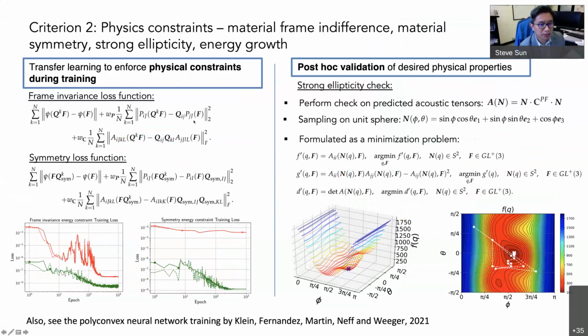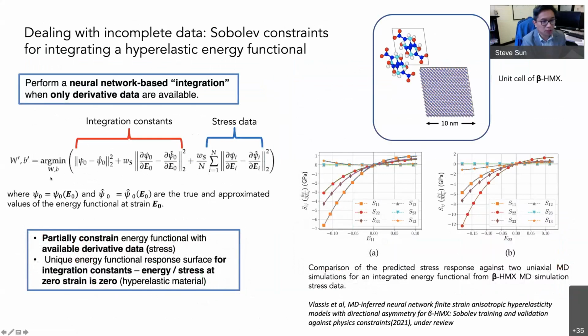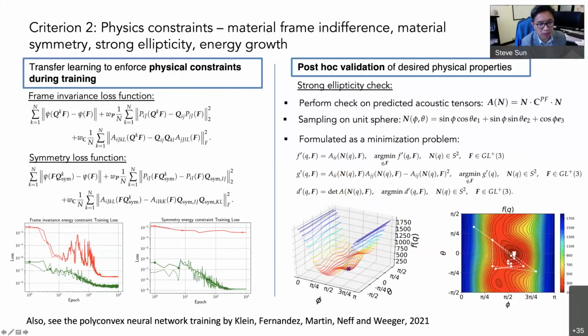So here we basically try to enforce two things, the material frame indifference and the symmetry. We introduce a test where the rotation tensor is put into the deformation gradient, and we check whether we can get the same energy when we change the observer orientations. And we also check whether for the symmetry rotations, we can maintain the same constitutive response.